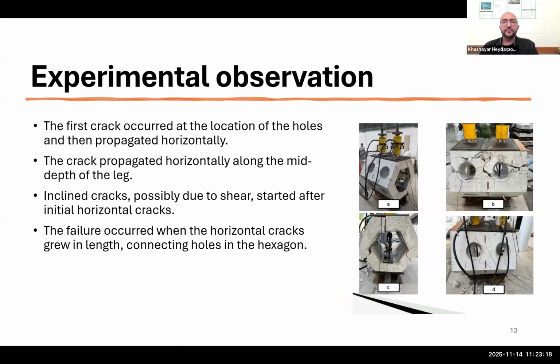And it was observed from this experiment that the first crack occurred at the location of the holes and then propagated horizontally, as you can see from the image. Image B, the crack propagated horizontally along the mid-depth of the leg. Also inclined cracks, possibly due to shear, started after initial horizontal cracks, and the failure occurred when the horizontal cracks grew in length, connecting holes in the hexagon.